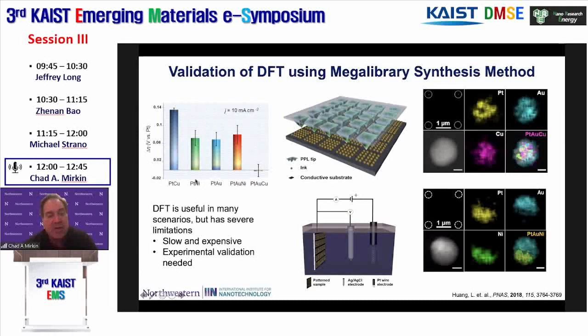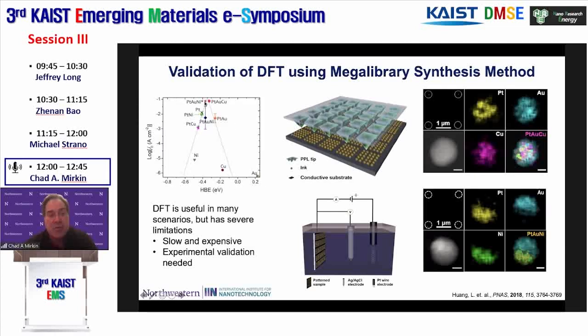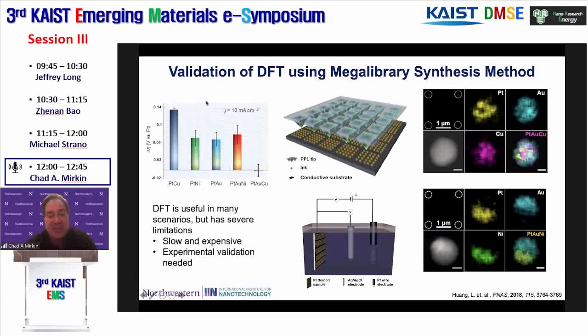Platinum, copper, not very good. Platinum, nickel, not very good. You want to be as low as you can on this particular graph because the baseline is platinum. Platinum, gold, nickel, which if you go back to this plot, that was one of the ones he predicted is at the tippy top. It's not very good. But platinum, gold, copper is in fact as good as platinum and is a record on a per platinum atom basis, or was at the time.